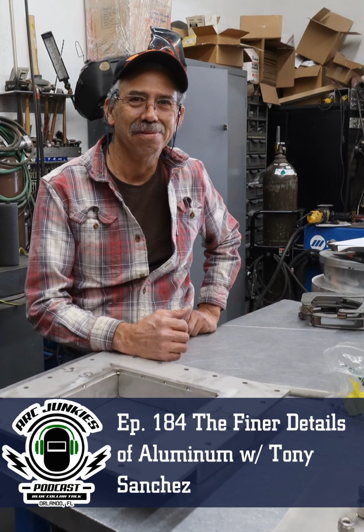And you've probably seen it in steel. It kind of boils a little bit and then drops back in because it's fighting that mass, that little bit of mass you put in there. As soon as that drops down in, you'll watch the puddle go to concaved again. And once that starts happening, about the third drop in there, you got control of it. Then I call that your heat hole, is what I call it. It's almost like you're running that little high heat in that aluminum all along, and you're trying to keep that thing pushed down there and packed into place.